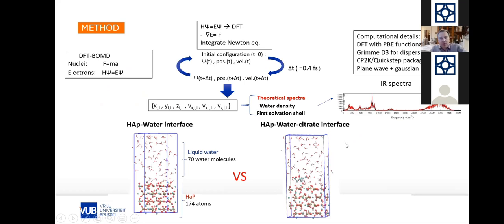Some technical details for those who are interested. So again, PBE functional with corrections for dispersion, the CP2K Quickstep package, and then the basis sets. The idea is that with our molecular dynamics, we extract the change in dipole moment at every step in order to obtain this kind of spectra. And we will compare it with and without citrate. So the water-apatite interface with the citrate that you see here.